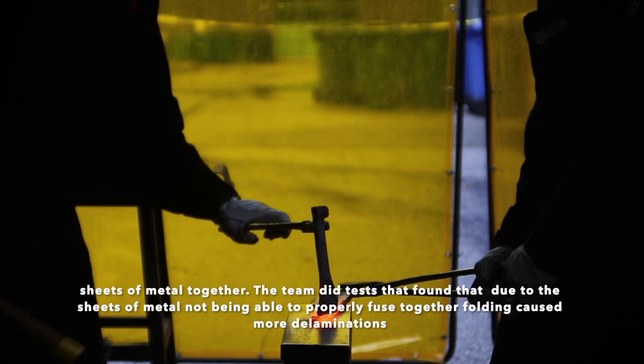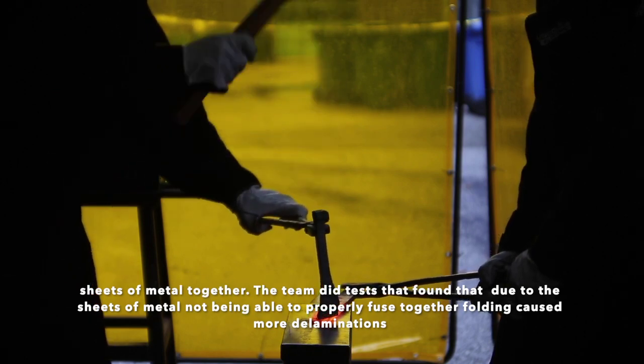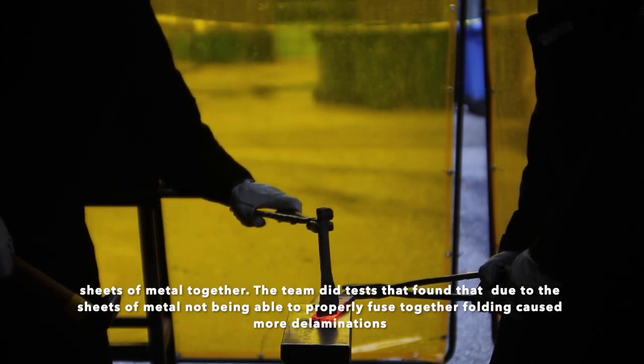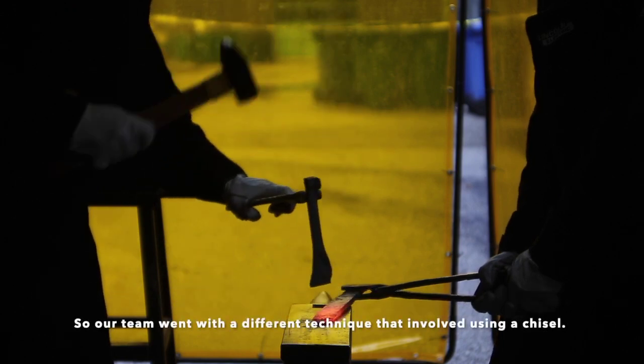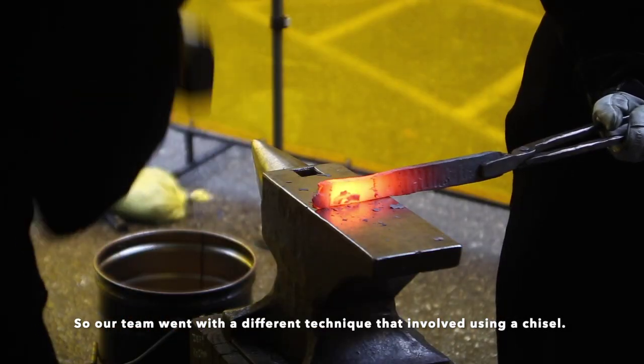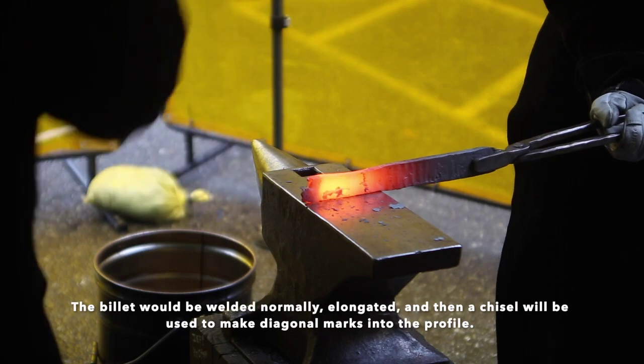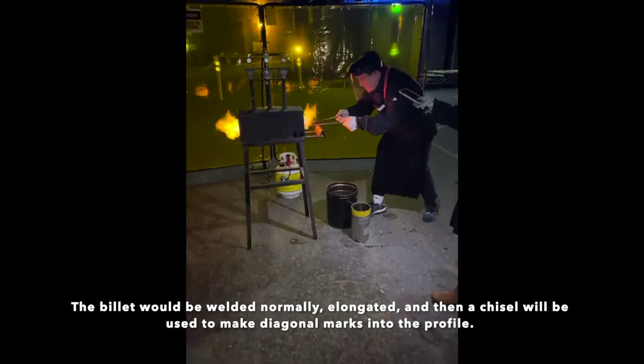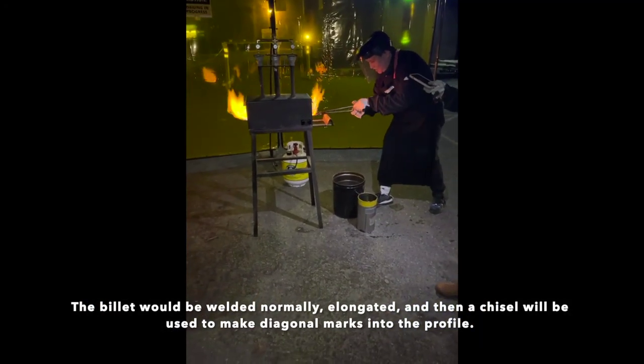The team did tests in the summer and found that, due to the sheets of metal not being able to properly fuse together, folding caused more delaminations. So our team went with a different technique that involved using a chisel. The billet will be welded normally, elongated, then a chisel will be used to make diagonal marks into the profile.